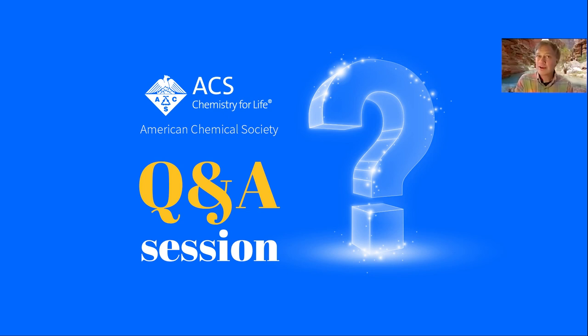And I'll just give one example. For water oxidation, we've been finding that we can put a very thin layer of the oxide on top of the molecules using atomic layer deposition typically. And surprisingly, it doesn't shut off the catalysis. The layer is thin enough and porous enough that molecules can get in and out, and the stability improves. It's still not a stability that's practically useful, but at least gives us some hope that with continued fundamental study, we could realize that.